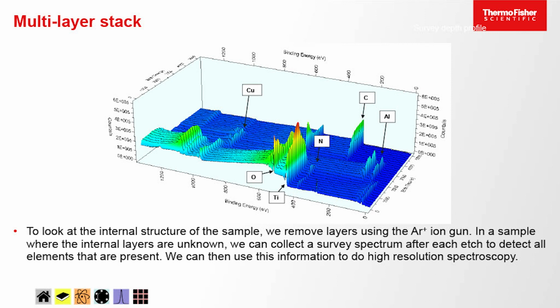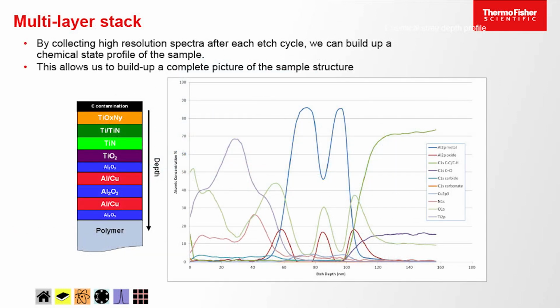So this is the surface, and this is deeper into the sample. As we go from the surface, we start off and we see titanium oxide, and then we go through, we see a bit of nitrogen, there's some aluminium, some copper, carbon, and so on. Once we know what's there, and we've done this experiment quite quickly, we can then collect high-resolution spectra and build up a chemical state profile of the sample.